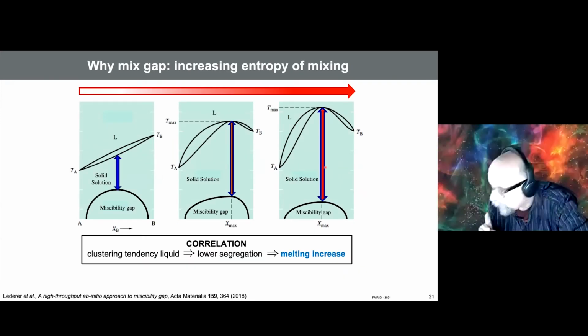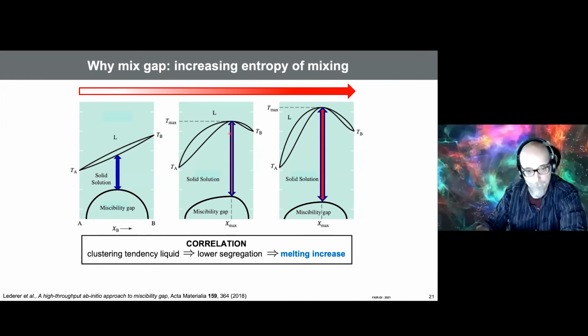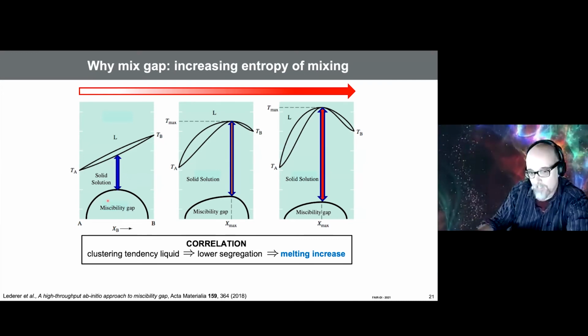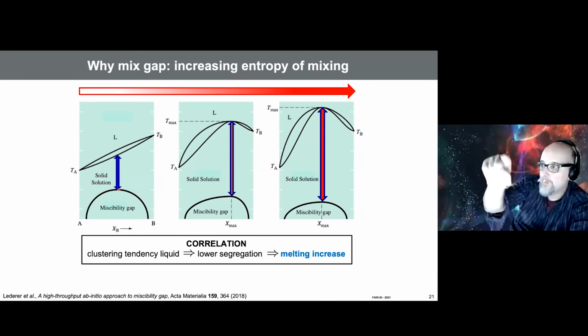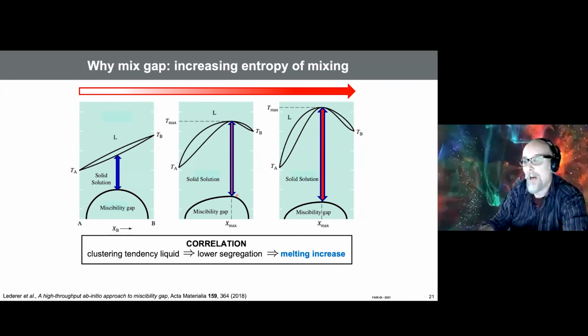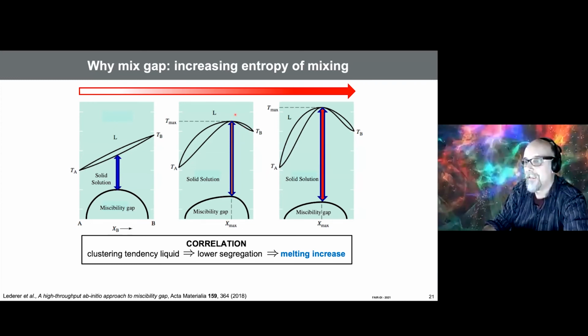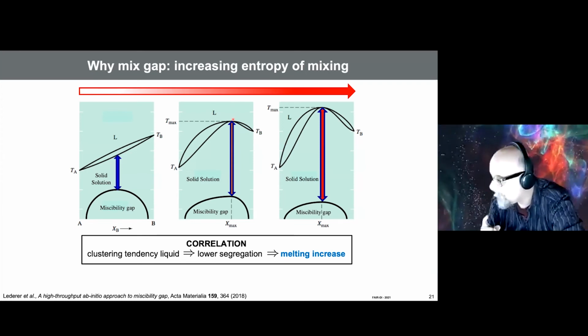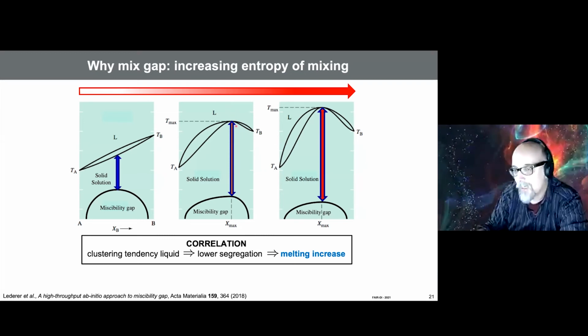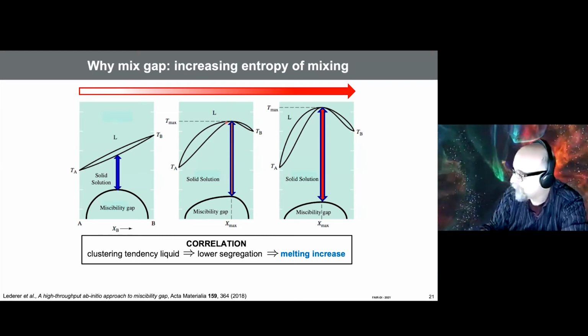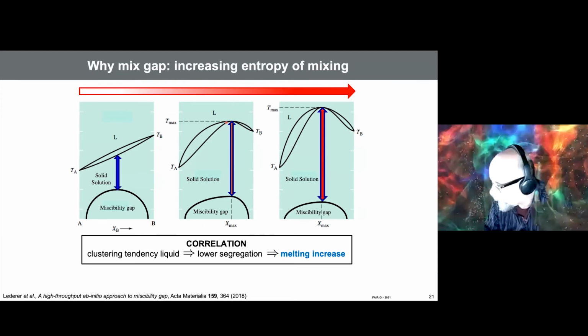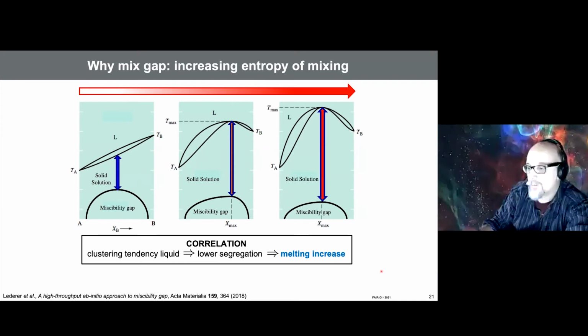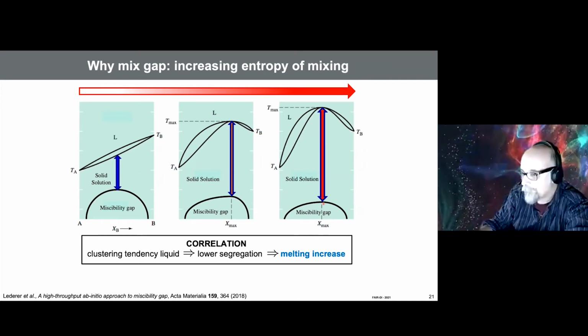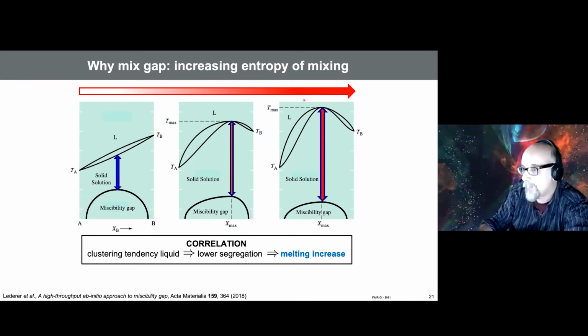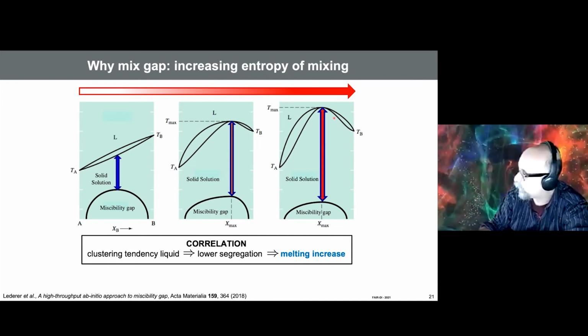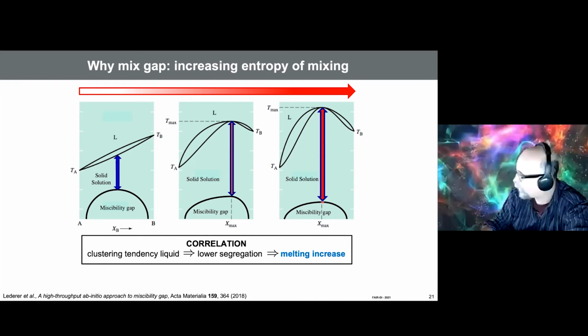Okay, so what about if we are looking for super high temperature materials? And that's why we were sponsored. If you are God and you already have a solid solution and a little bit of miscibility gap, and you're able to put your finger on the miscibility gap and bring it down, wow, I bring this down, so I'm going to bring up the congruent melting. And that's why we were studying this miscibility gap, because instead of calculating the melting point of these super high melting materials, or even making the experiments, how can you make the experiments of a 4,000 Kelvin melting object, right? It was much cheaper to guess the miscibility gap, and find a relationship between this point and this point. You just go in literature or with calculations, you find a relationship between this arrow and this point, and then you are done.